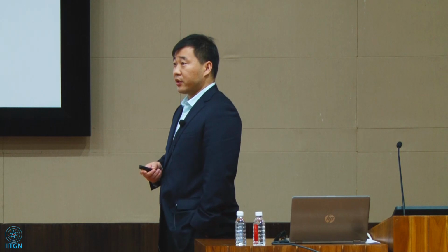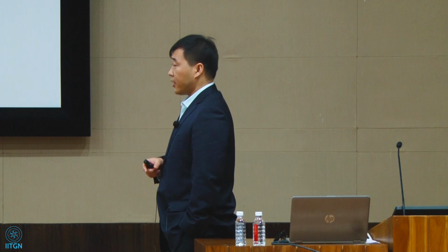The second section is the element testing of the MICP. Now we introduce the two ways of preparing the MICP specimen. The first way is using the bacterial solution and the cementation solution separately. We first pour the bacterial solution into the specimen and make sure that the bacteria adhere to the sand surface. In the next step, we pour the cementation solution onto the sand, so that the biological and chemical reactions take place in this process. After about 5 hours, we can remove the PVC tube.